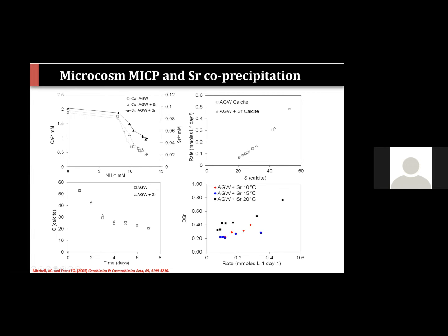Okay. Now we see that that's broadly due to higher reaction rates favoring the incorporation of strontium relative to calcium, due to more indiscriminate ion incorporation at higher rates. And we also see larger co-precipitation and greater partition coefficients at higher temperatures, which is broadly due to the higher miscibility of ions at higher temperatures. Now, in these unseeded experiments, we generally see that rates are quite low at equivalent saturation states compared to many seeded abiotic experiments.